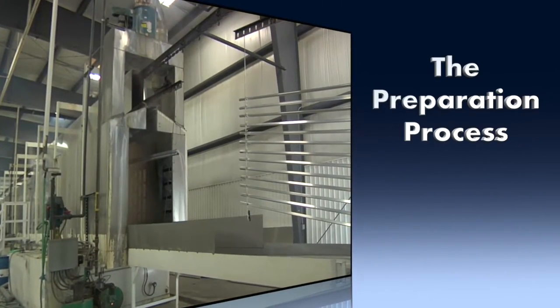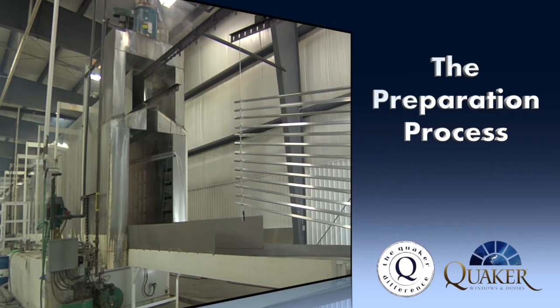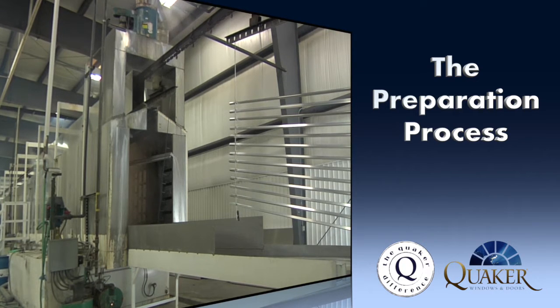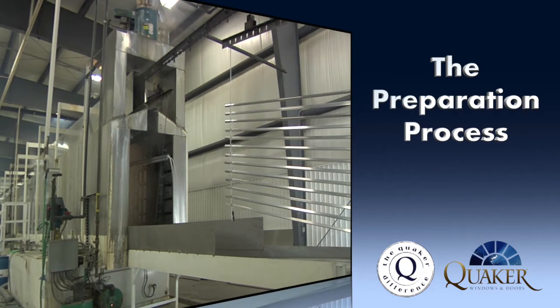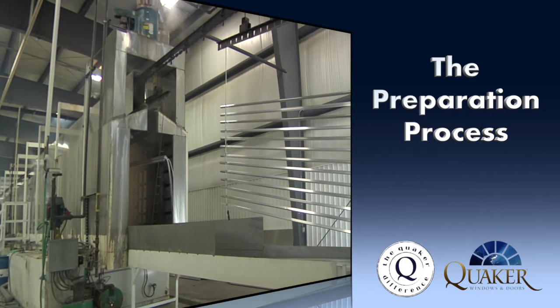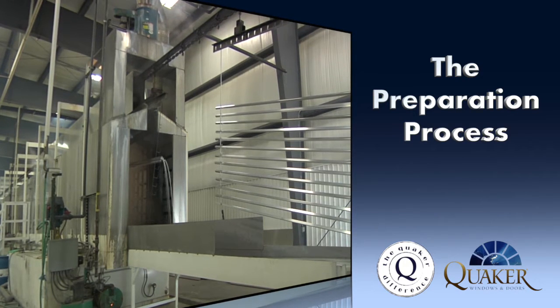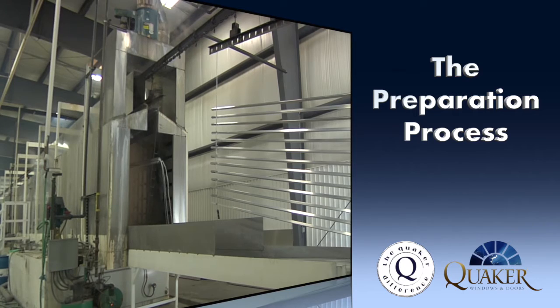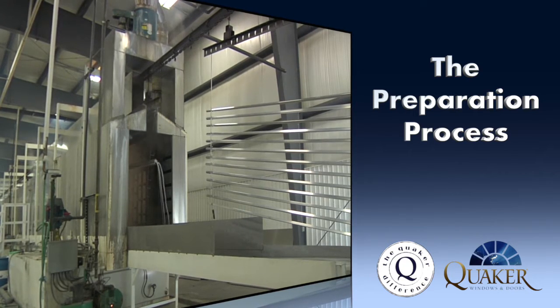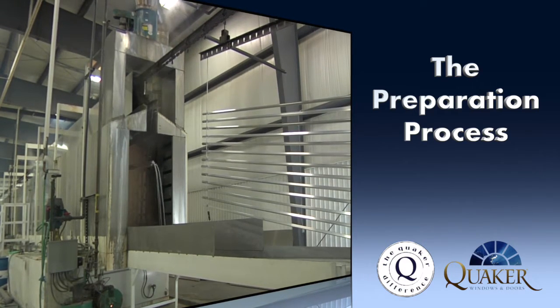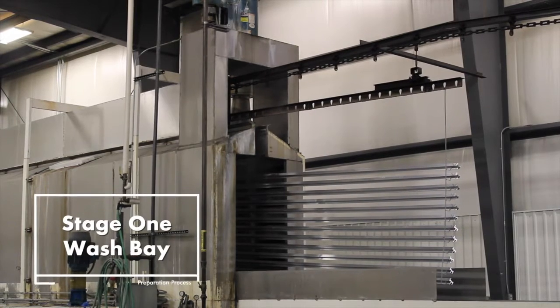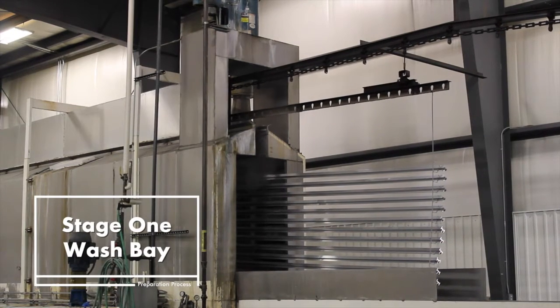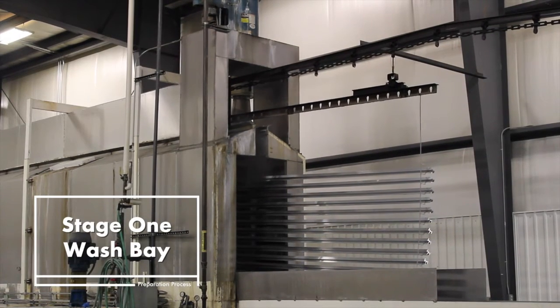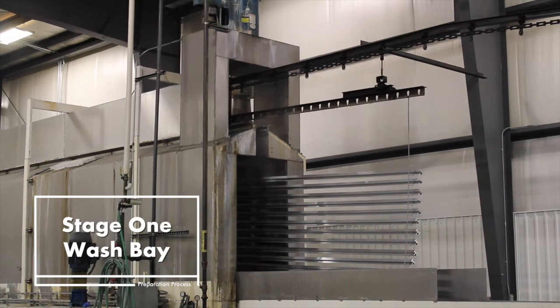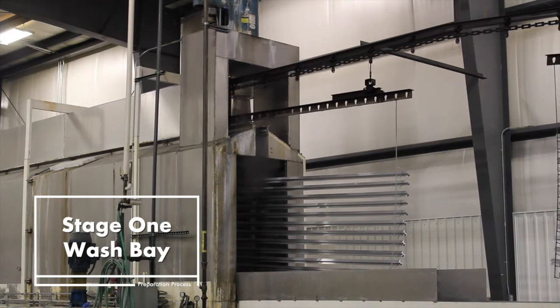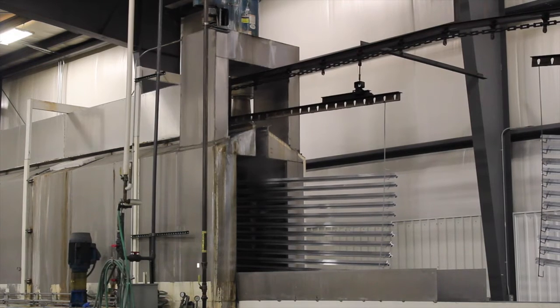Before aluminum material can be painted, it must be properly cleaned and prepped. What this requires is that all material to be painted pass through a 5-stage horizontal washer and pre-treatment system that'll both clean and prepare the material for the paint coating process. Stage 1 is the wash bay, where a special cleaning solution is used to remove all foreign materials such as dirt and oils from the surface and prepare the aluminum surface for further treatment.